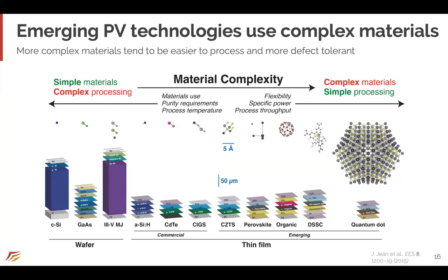One way is to use material complexity as a guiding metric. This is very hand-wavy, but you can look at a spectrum from things like crystalline silicon, which are wafer based and have relatively simple materials, single atoms in a unit structure in a basis, but very complex processing: very high temperatures, crystallization, doping, things like that. On the other side of the spectrum, you have things like quantum dots and organic molecules, which are very complex if you look at the building blocks of these materials, but they are processed in very simple ways at low temperatures.